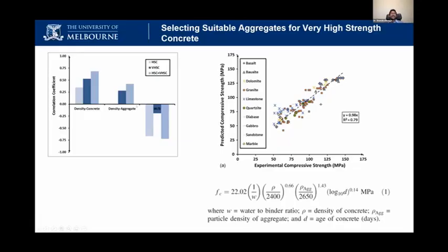Then we also did the same analysis, and we found that for very high strength concrete, the density of aggregate really matters. Then we came up with this equation to design high strength concrete, so we incorporate the aggregate effects there. This can be a very simple equation for practitioners in the industry, the material engineers, to start, or to know what the right water to binder ratio is and what the aggregate is. This is a preliminary step to develop high strength concrete.